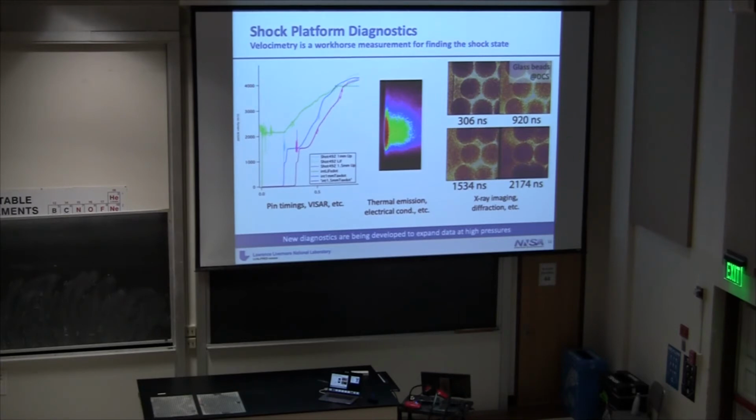All this is basically imaging with X-rays. You can also do diffraction, pretty much any other thing you want. If you can shine X-rays at it and you can detect it, you can do it. Spectroscopy has become pretty hard here simply because of collection times. Normally if you shine some photons in on something, you may shine 100 photons in. With something like diffraction, you get a lot of photons back. With something like imaging, you get almost all the photons back. But with something like spectroscopy, you're getting 1 out of every maybe 10^4 photons back, or maybe even fewer. So spectroscopy isn't done quite as much in this, or that's something we're working on as a field.